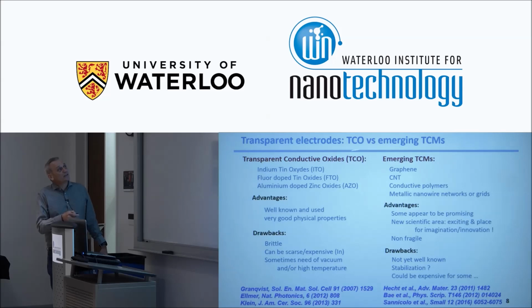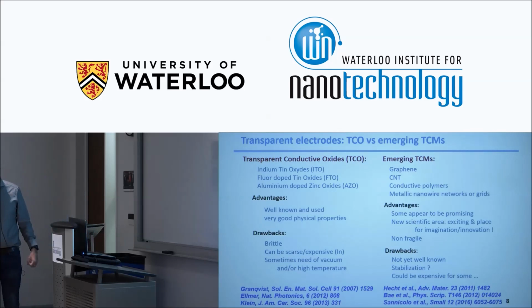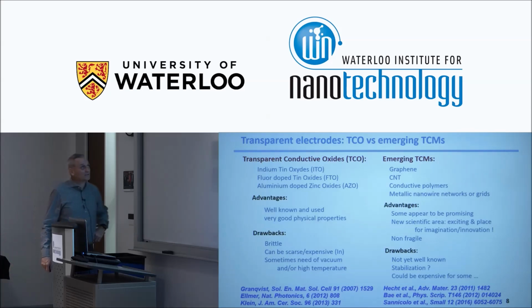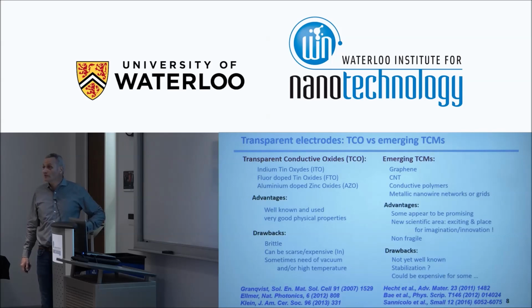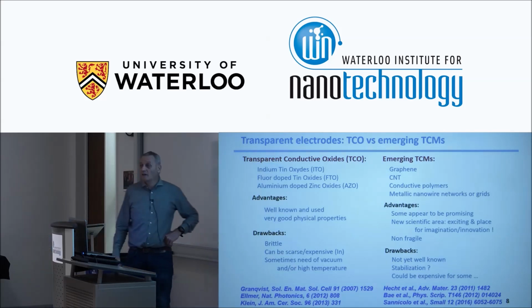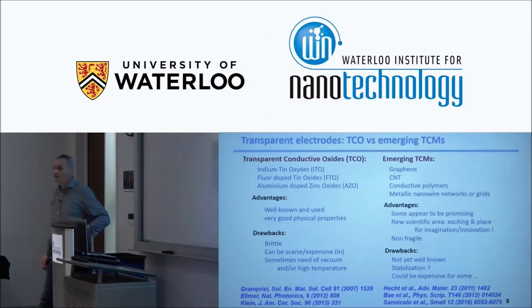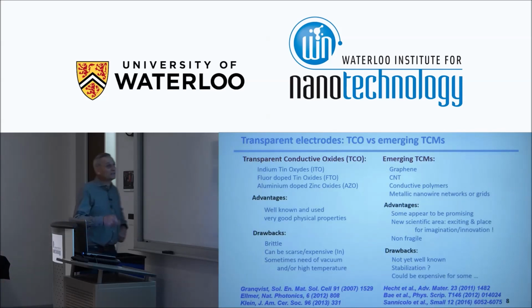So the main material family concerns transparent conductive oxides. They have been used and investigated for, let's say, 4 or 5 decades. And the three big boys are indium tin oxide, ITO, fluorine-doped tin oxide, FTO, and aluminum-doped zinc oxide, AZO. The advantages are rather well known. They've been rather well investigated, and they can have good or even very good physical properties. Drawbacks: they are oxides, so by nature they are brittle. And some of them could be scarce or rather expensive. That's the case of indium. This is why we would like to stop using ITO. And often we need a vacuum to deposit them, and often high temperature as well.